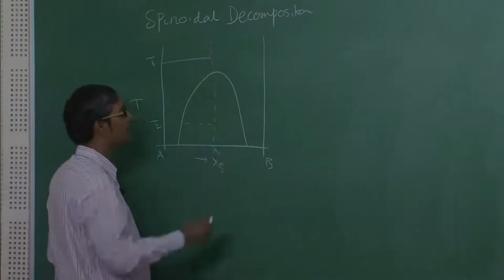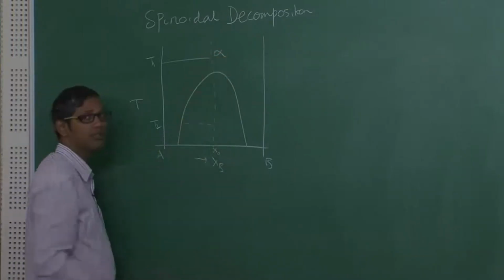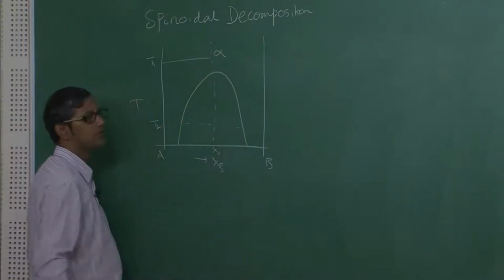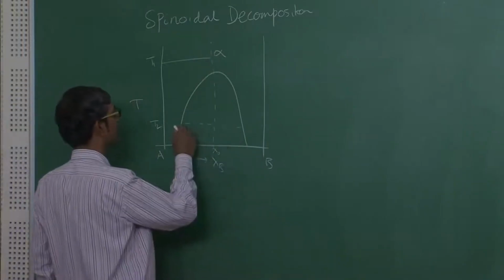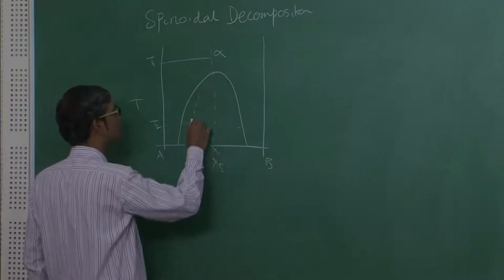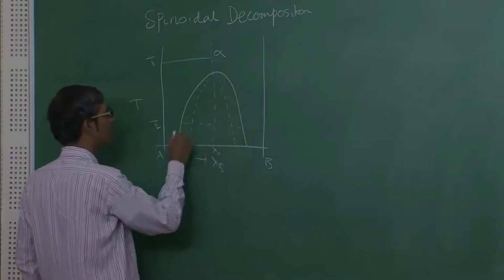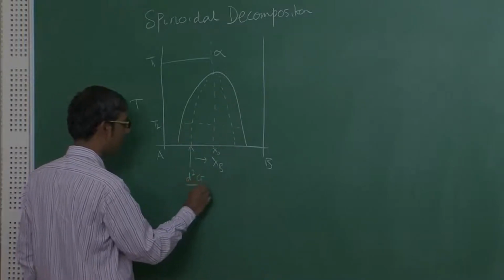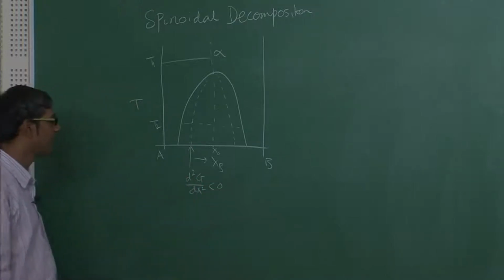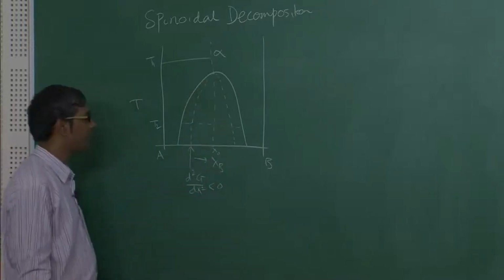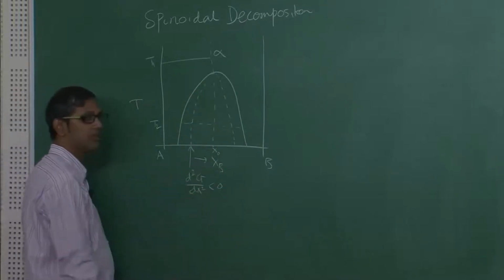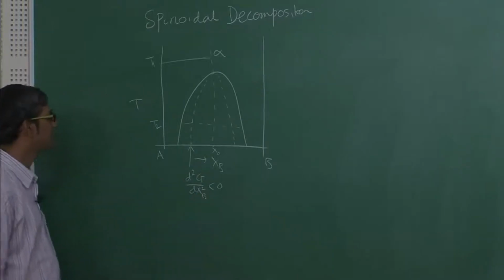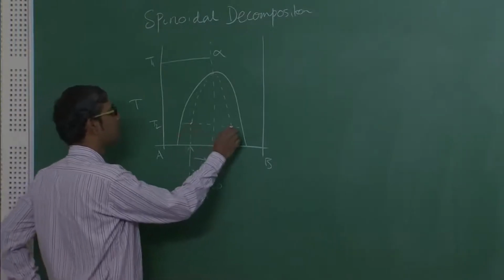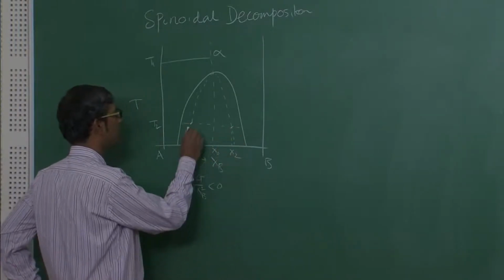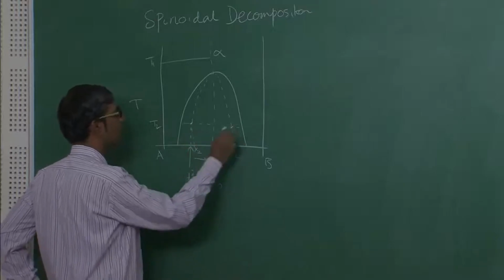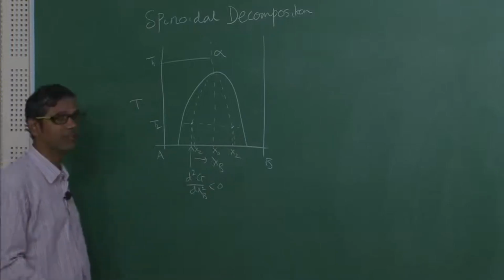Now, it is very evident that as you quench this alloy from high temperature, which has a single phase solution alpha, it is going to decompose into two different phases with compositional fluctuations. As we have seen, there is a chemical spinodal within which this decomposition happens, because the double derivative of free energy with respect to composition is less than or equal to 0. That means the curvature of the free energy curve as a function of the composition variable x_B is negative within this. So, these are the 2 points x1 and x2 at which the alloy will decompose without any need of nucleation or growth. That is what is called spinodal decomposition.